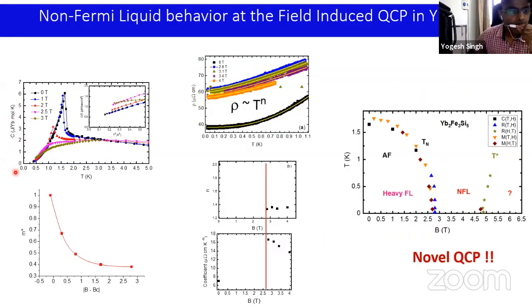So I call your attention to this graph, C versus T at various fields. So at low temperatures, you can see that as field is increased, the Sommerfeld coefficient is increasing, okay, as one approaches the critical field, which is this brown curve. So if I plot the gamma versus distance from the critical point, so the magnitude of B minus BC, I will see that when B minus BC is 0, I am at the critical point. So the effective mass seems to be diverging as I approach the quantum critical point. So something anomalous is happening, as has been seen for many other quantum critical magnets. What about the phase 2? So we have established that we have a heavy Fermi liquid in this region 1, and the effective mass diverges as we are approaching this critical point.